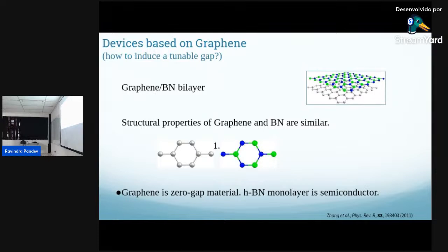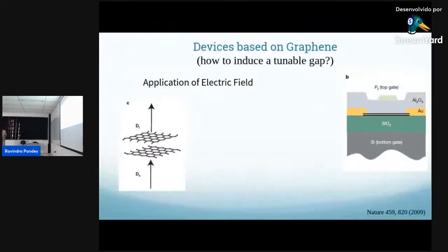Question: every time that you create a non-homogeneous charge distribution in the system, do you need to create a band gap? That's the rule in graphene, because this came out from the experiment. That was the whole idea. In the graphene bilayer, they apply the field. This layer experiences a different field than this one, so they have a different degree of perturbation. Because ultimately, the bands come from the overlap of electron density. If they are the same, they like each other. If they are slightly different, they start disliking each other. That's a gap.